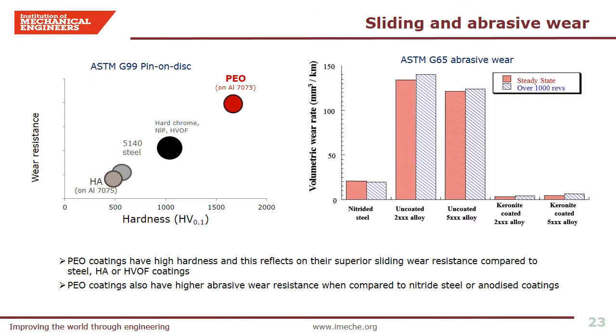This slide shows sliding wear resistance comparison of various hard coatings against steel. The vertical axis is wear resistance and the horizontal axis is surface hardness in Vickers. The plot clearly indicates increasing sliding wear resistance with increasing surface hardness. HVOF coatings such as tungsten carbide cobalt chrome are considered a replacement for hard chrome plating and offer substantial wear resistance for steel as well as aluminum. But it is the PEO coating that, due to its substantially higher hardness, adhesion and flexibility, offers much improved wear resistance in comparison. The column chart on the right shows abrasive wear rates of various materials, suggesting that PEO coatings can offer better wear resistance than hardened steel, thus enabling light materials to potentially replace heavier steels.